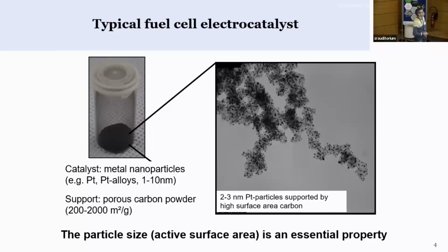You have an active phase that are metal nanoparticles. These are the darker dots here. And they are relatively small, in the range of a few nanometers. Mainly it's platinum and platinum alloys in applications. And you need to make these particles small in order to have a large surface area where the reaction can happen.